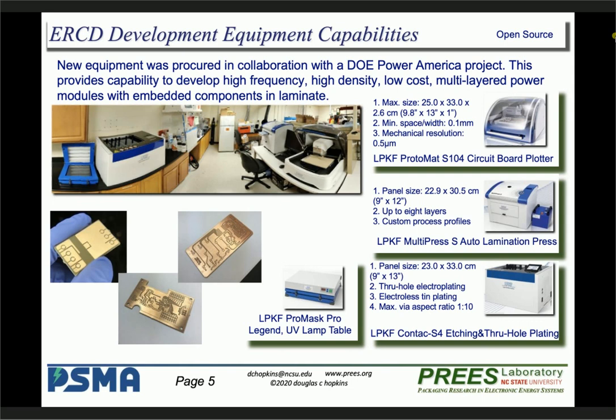Again, it's like making printed circuit boards, but instead of using polyimides, which are hygroscopic, we're using epoxies. It doesn't quite have as low a modulus as polyimide, but it has a very, very low modulus compared to ceramics. So when people talk about CTE, a lot of EEs talk only about CTE, coefficient of thermal expansion. What you really should be talking about is the expansion coefficient along with the modulus, because rubber's got a horrible expansion coefficient, but it's so soft, it never translates stress. So you want to look at soft materials to be able to say, hey, I can go long times at high reliability without having to translate stress into my die or into my solder joints, etc.